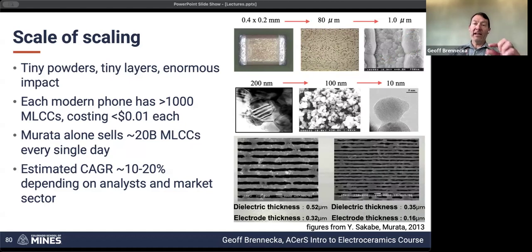We don't want the electrode layer thickness to be too thick because that just takes up more volume that we could be using for energy storage. But you need the electrode layers to be thick enough that they can get the charge, the electrons, in and out as fast as necessary. So the thicker the electrode layer, the higher the operating frequency can be. The thinner the electrode layer, the more capacitance you're able to get per volume. So it's a balance, just like everything else.